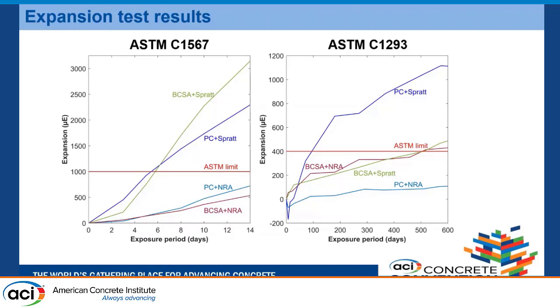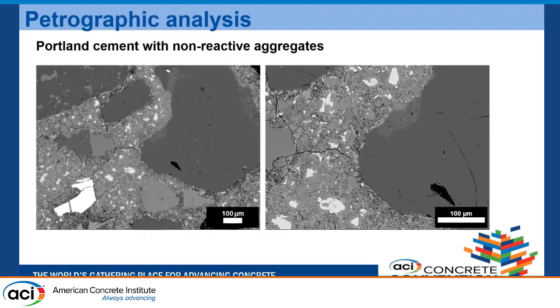It can be something with the reaction product that needs to be looked upon. So we can't just state that it is ASR just because it has crossed the limit. But again, to confirm the results of this test, I have done petrographic analysis. The petrographic analysis is done on the long-term test specimens to find ASR cracks, and what I've done